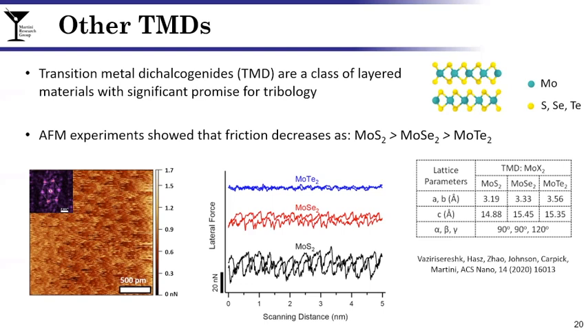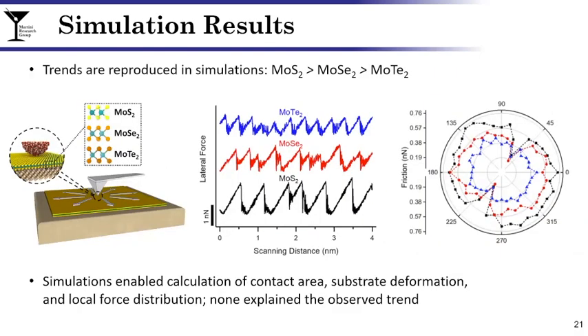In the middle, you're looking at the lateral force as a function of scanning distance, again from AFM, and we see, surprisingly, that MoTe2, excuse me, has the lowest friction and MoS2 has the highest. This was repeated in the simulations. On the far left is a schematic. In the middle, we see the simulation results. And again, the MoTe2 has the lowest friction of the three and the MoS2 the highest.